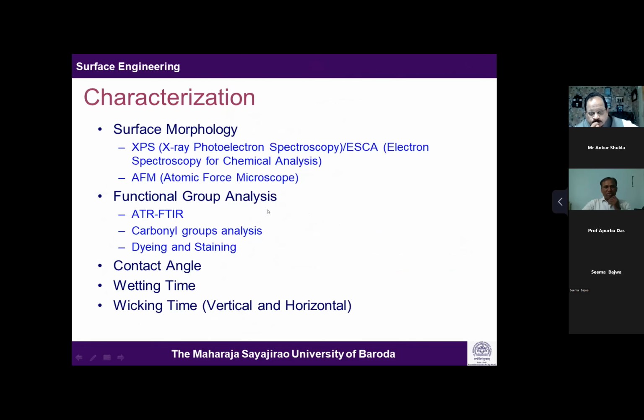So this is something about the type of plasmas. Coming to the characterization part, we have a number of methods for surface morphology, chemistry as well as physics. X-ray photoelectron spectroscopy gives a very precise analysis of the change in the atomic composition at the surface. Atomic force microscopy gives the finer-level change in surface roughness. There are other methods like ATR-FTIR and carbonyl group analysis, and simple methods like contact angle and wetting time, which is the simplest method, but we can learn about the change in the surface energy.